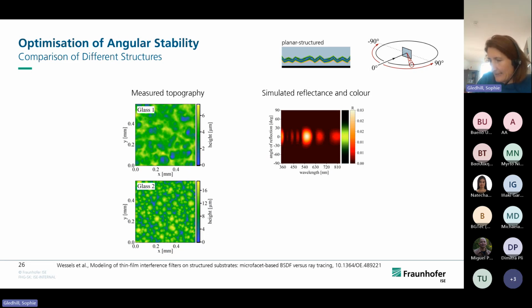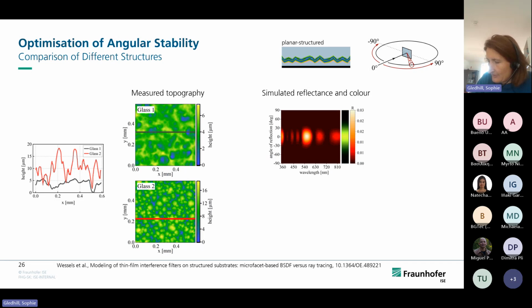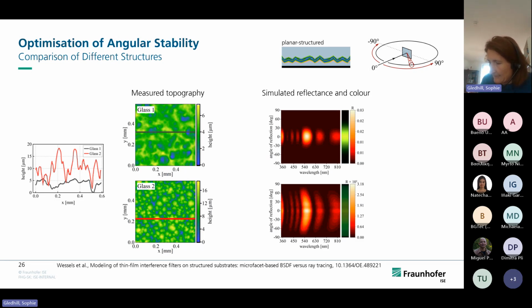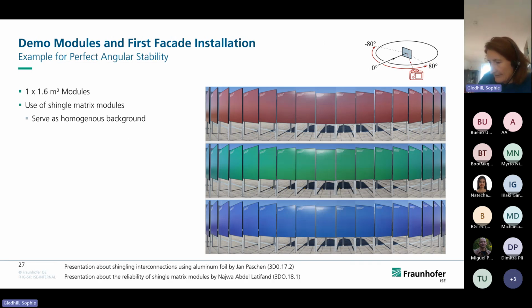If we now introduce a second structure and compare by looking at the cross section, this second structure shows much steeper slopes, so we anticipate much stronger scattering. And this is exactly what we see in the model and what we measure. By using this structure, the color is distributed across the whole angular range, resulting in the aimed homogeneous appearance. Here one can see that the peak spreads out for wider angles. And we can see this visually in the project. Here we have a color camera, which is used to photograph our improved demonstrator modules at different angles to the perpendicular, so plus and minus 80. And we really achieve a good color right out into almost 80 degrees.